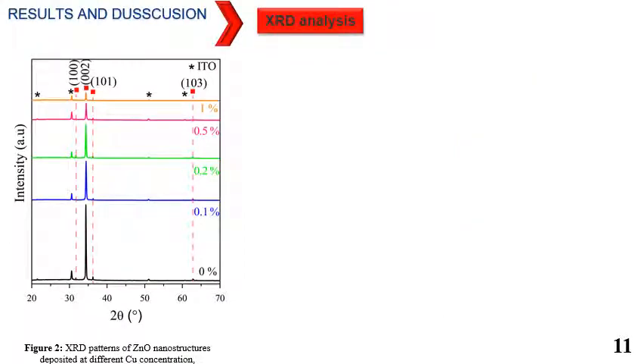The crystallographic structure of pure and copper-doped zinc oxide was investigated by X-ray diffraction. As can be seen, the sharp and intense peaks correspond to the wurtzite phase of zinc oxide, which reveals the high crystallinity of the samples. The XRD spectrum shows a preferential orientation along the 002 plane, suggesting that the crystalline grains are mainly oriented along the c-axis. The intensity of peaks decreases with increasing copper concentration, which can be explained by the slightly smaller ionic radii of copper compared to zinc ions.